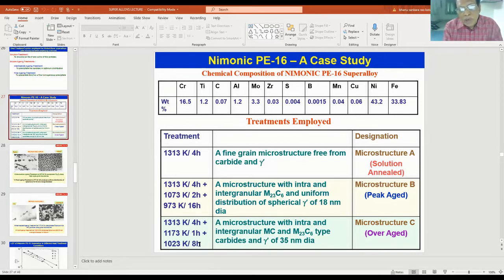Since I am applying higher temperature, gamma prime gets coarsened in the case of microstructure C. But full precipitation of gamma prime will occur at low final aging temperatures. So in microstructure C, still some amount of gamma prime forming elements are there in the matrix. But when you go to high temperatures during service, they may precipitate as gamma prime.